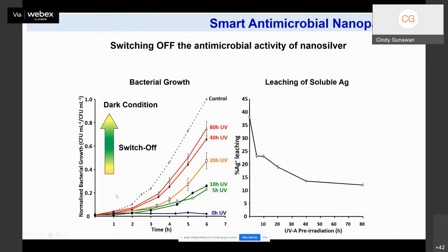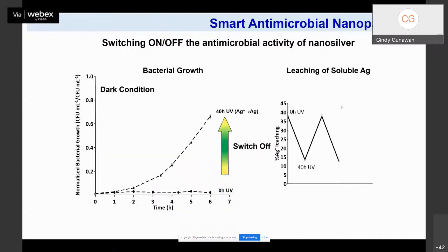So the switching off of the antimicrobial activity actually matches with the leaching of soluble silver. Here we could see at 0-hour UVA illumination, it means as-prepared nanoparticles without any UVA illumination, you could see about 38% of leaching here. And when you increase the UVA pre-irradiation, you could see less and less release of soluble silver into the system. And as you know, soluble silver that is released from nanoparticles is also toxic. So we have seen how the antimicrobial activity has been switched off.